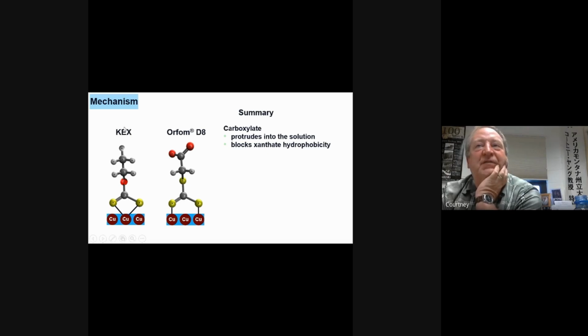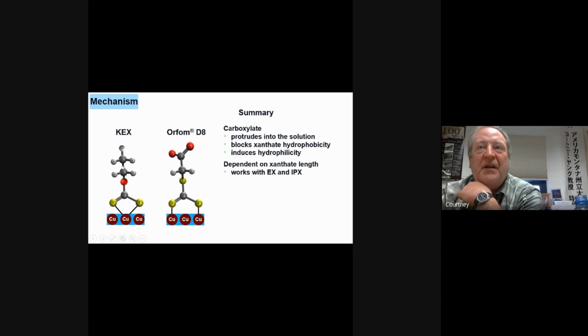Hydrophobic forces do not reach very far into solution, where anionic or electrical forces will reach much further into solution. And this is why it can mask the hydrophobicity of the ethyl xanthate that's adsorbed onto the chalcopyrite and depress it. So it induces hydrophilicity, and depending on the xanthate length, if I went to isopropyl xanthate, I included another carbon in here, we expect that we would also see depression still. But if we went to amyl xanthate, it probably wouldn't work very well, because then the xanthate molecule is too long. But that's some research that has yet to be done.